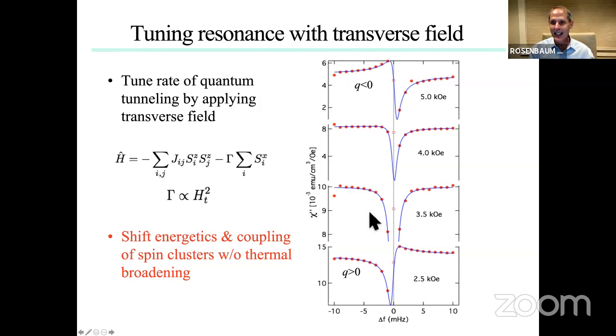So here you see a sequence of Fano resonances at a series of transverse fields from 2.5 kilogauss to 5 kilogauss. Now, let me point out a couple of things. If I look at one limit, say the 2.5 kilogauss limit, I have an asymmetry about 0 as I move off from the drive frequency. That tells you Q is in one limit. Remember, it goes from -1 to +1. We call this greater than 0. That's sort of arbitrary. But at the highest transverse field, I've gone to Q less than 0, okay? Because it's now on the other side of 0, the asymmetry. And so somewhere in between 2.5 and 5, Q goes to 0.